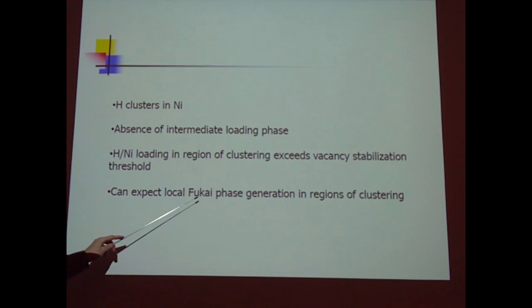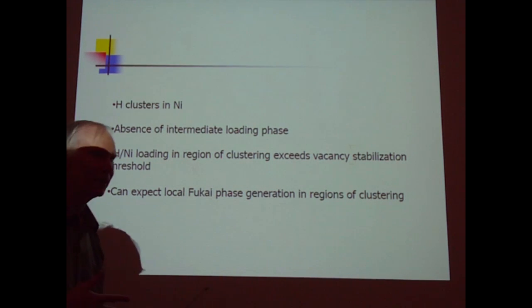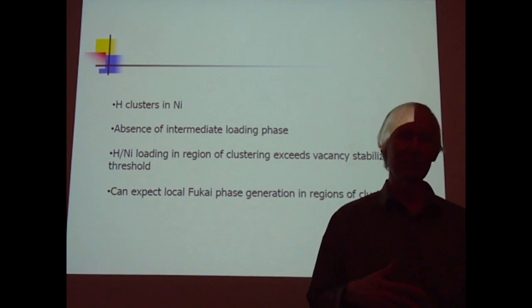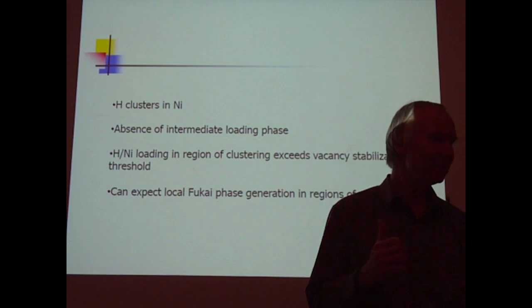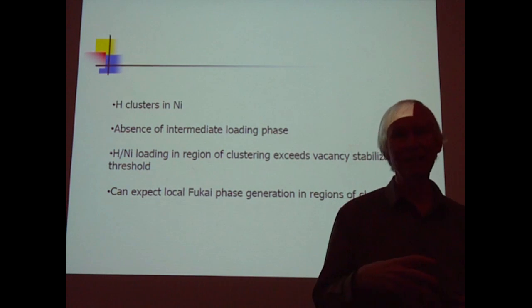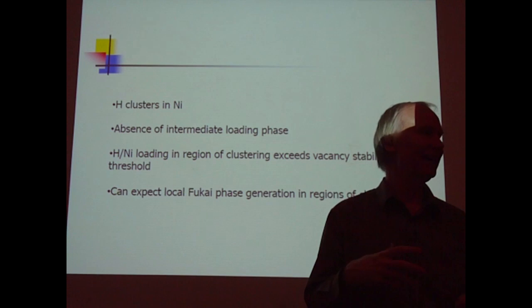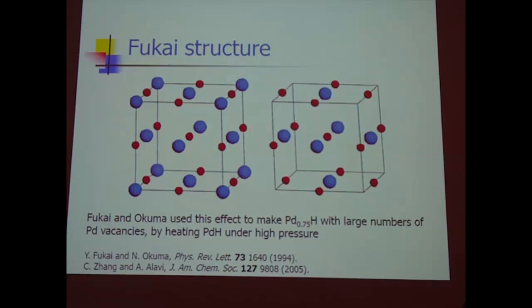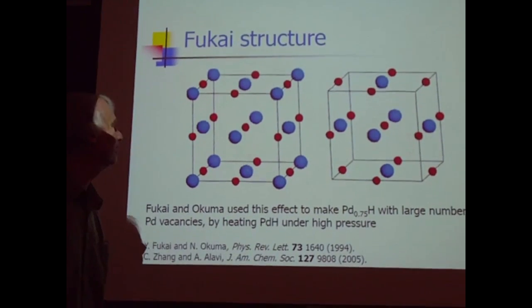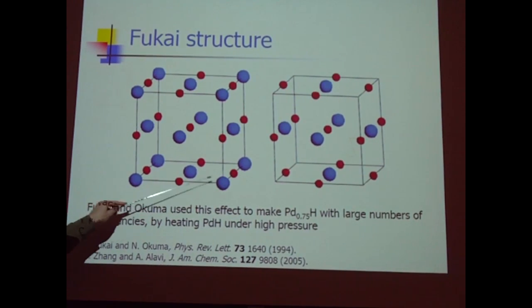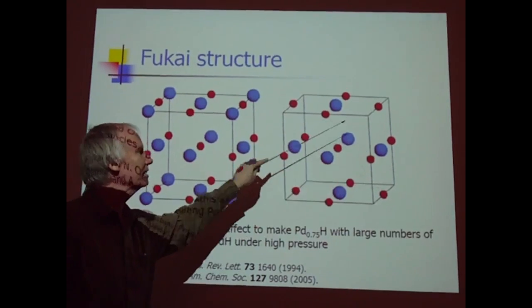So we would expect Fukai phase generation in nickel hydride if you can have the vacancies move. I mean, the whole game in the Fleischmann-Pons experiment, as we were arguing before, was to make vacancies, which we did with high loading and co-deposition. Well, in nickel, all you've got to do is put in a little bit of hydrogen clusters to exceed the vacancy stabilization threshold. Now all you've got to do is arrange conditions so that the vacancies can move. And if you can, you'll get natural formation of the phase structure. Now we recall that this phase structure takes the host metal nuclei and in an ordered fashion replaces them with vacancies. So this is the kind of thing that we're talking about for nickel hydride.